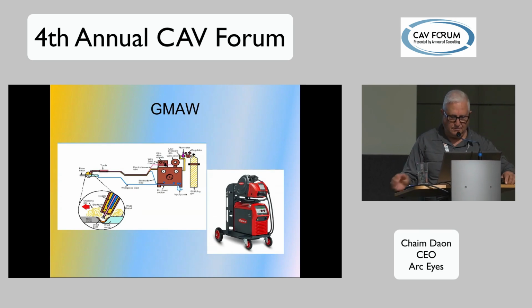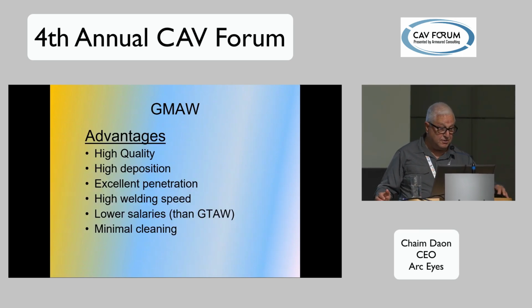The advantages, because there are advantages. We have high quality. We have high deposition. Deposition, again, is the amount of wire that goes into the weld, as far as the amount of wire that goes through the machine. There is spatter, and that will lower the deposition, but it's still considered a high deposition process. You have excellent penetration.